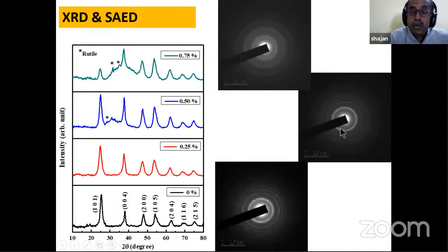And it is identified that there is a phase change from the anatase phase of titanium to the rutile. And you know, rutile is the more stable. So when we start adding the MOF to this, the phase changes from anatase to rutile. And that is reflected in the electron diffraction images also.